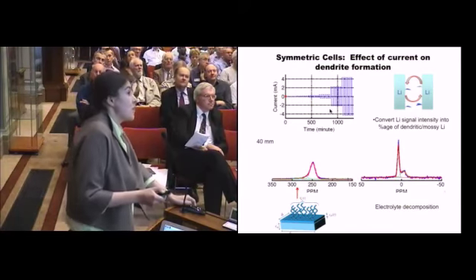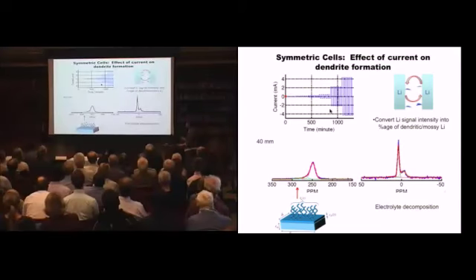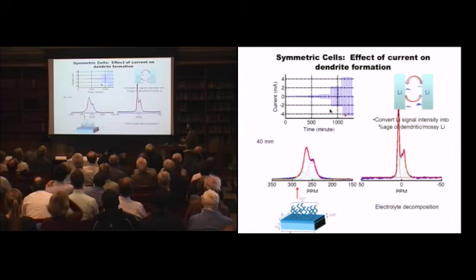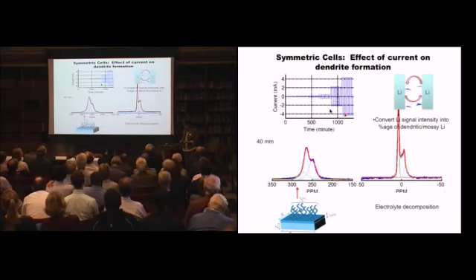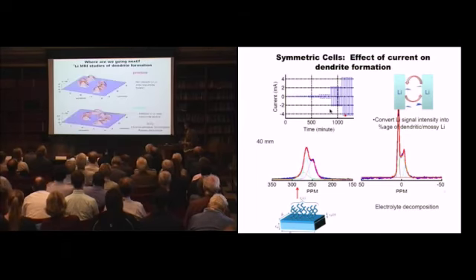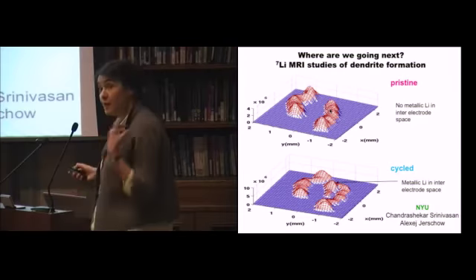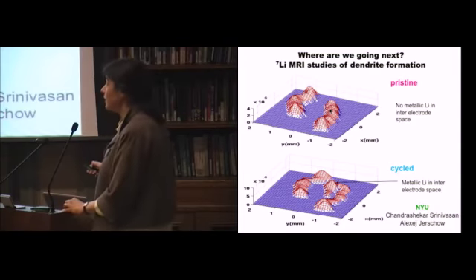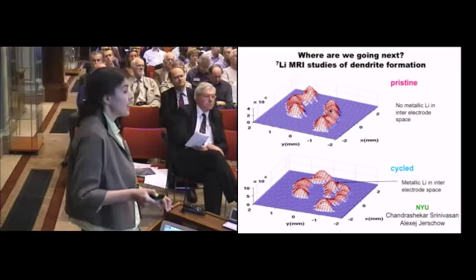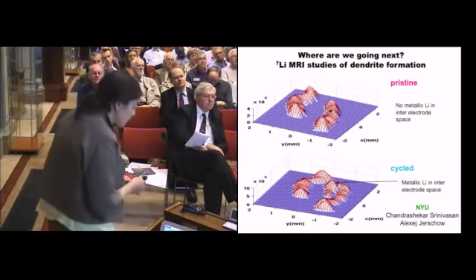So this is a movie that sometimes works. This is an experiment where we're now seeing what sort of current you need to produce dendrites. So I'm going backwards and forwards, and here's the lithium signal, and you can see when the current goes up, you can now start to see the formation of the dendrite come up here. Again, before you see any signature of decomposition from the electrochemistry. The next thing we wanted to do to really help understand this process was to work out where the dendrites were occurring. In order to do that, what we're doing now is MRI, just to return back to the original technology. And so here's the formation of the lithium dendrite as I cycle the battery backwards and forwards.